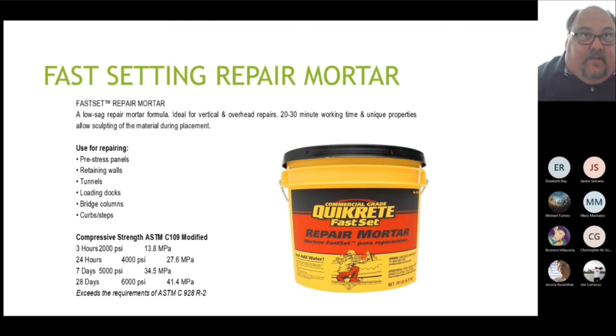If you are repairing something that's over 2 inches, definitely make sure it's rebar reinforced. If you come across a big busted out piece of a parking garage structure and there's rusted rebar, you need to make sure you clean the rust off that rebar because that will cause a crack. Forgot to mention that in the cause of the cracks too. That's another thing, corrosive rebar. When that rust happens, it creates a process that does actually cause cracks.